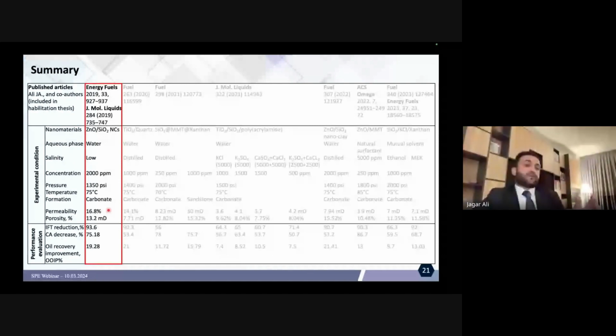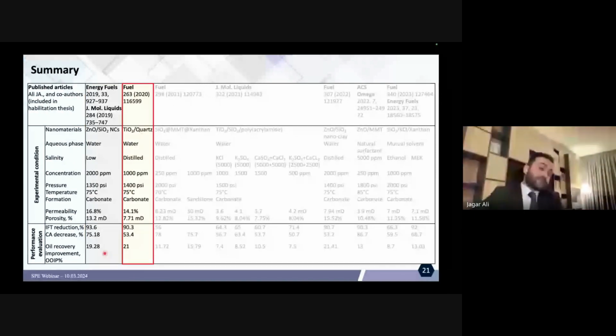For the first work, which was published by Energy and Fuels and Journal of Molecular Liquids, we used ZnO SiO2 nanocomposite with water at low salinity level. So the pressure was about 1,350 psi and temperature 75 degrees. The type of the rock was carbonate with this range of porosity and permeability. The IFT reduction is very high, which is around 93%. Although the contact angle decrease is not too high, it is water wet, below 90 degrees. That's why we have a recovery of nearly 20%.